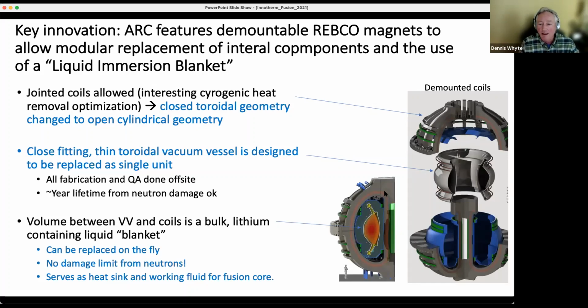So what does this lead to? Is that this thing that you see surrounding the plasma is basically the single solid material engineered component which is interacting with the fusion heat. It's a close-fitting, thin toroidal vacuum vessel, which is designed to be replaced as a single unit. So all the fabrication can be done offsite, and it can last about a year from neutron damage and then be replaced. So although most people are familiar with fusion design, this is a kind of radical approach, because in some sense what we've done is that we've minimized the solid materials that interact with the fusion environment by intentionally moving those solid materials up front, close to where they get damaged, but designing it to be replaced, not trying to make unobtainium.